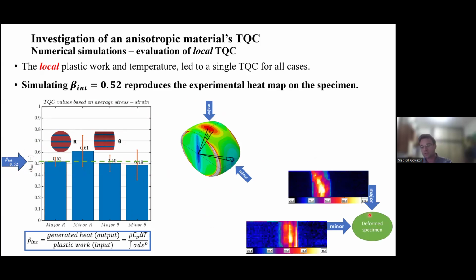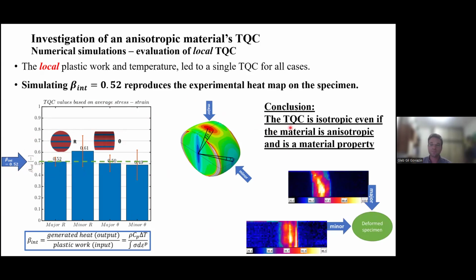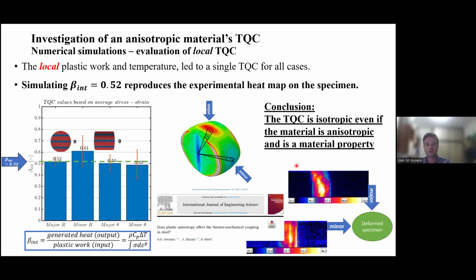So what I'm trying to say here is that we were able to present that the TQC is isotropic, even if the material is anisotropic. Thus, we were able to contradict previous studies. This study was published in this journal.